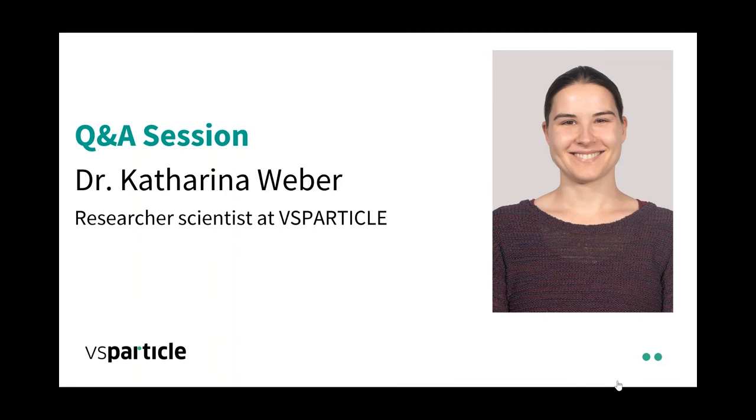We can use pure elements that are metallic or semi-metallic, so silicon also works. But we can also use alloys and a combination of elements. The important property here is that it has to be conductive, as it works with spark ablation.